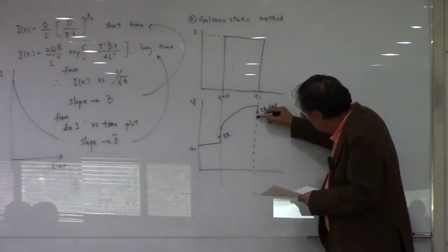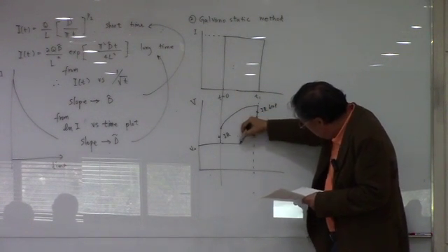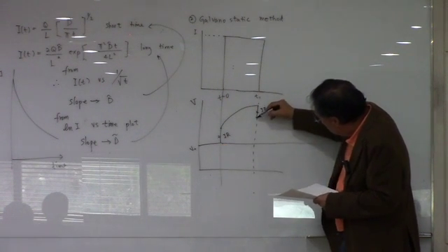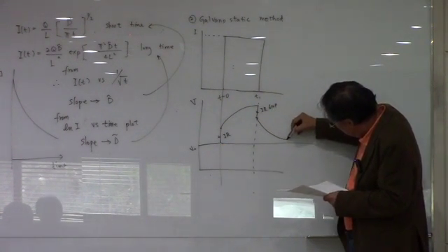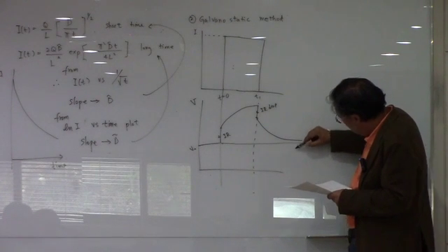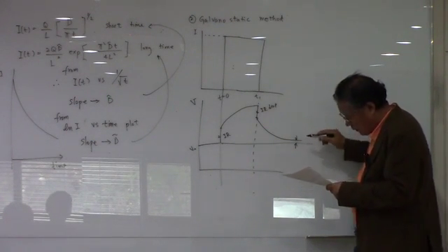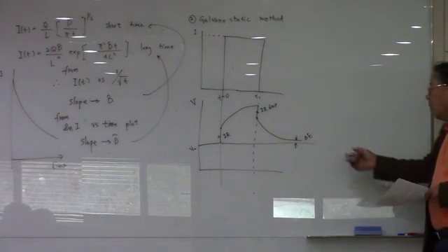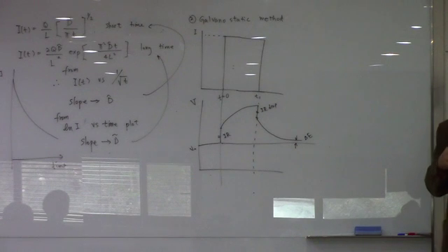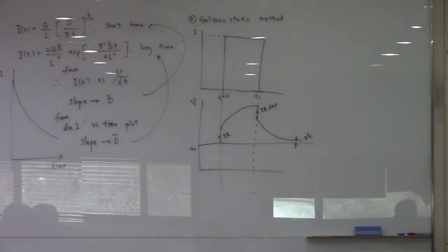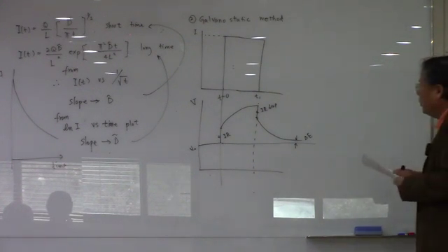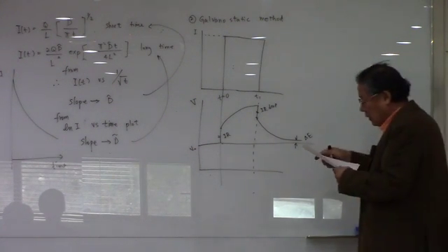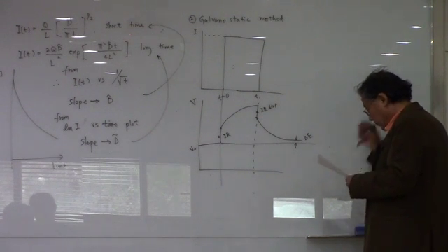And then it's going to decay to some point which is different now from this V naught to some value here. And then the difference here is going to be delta E. And that comes from the fact that you have inserted or removed the electroactive species by passing the current I naught in this galvanostatic method, okay?